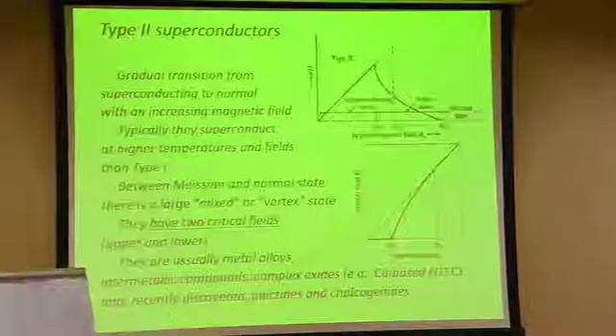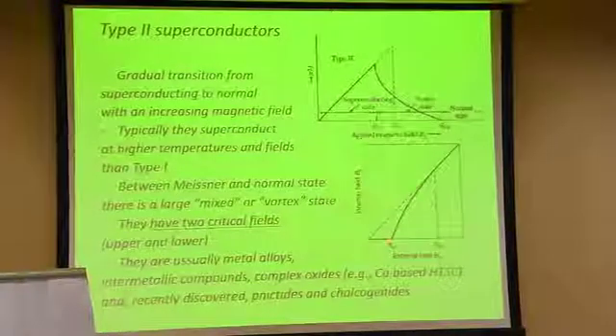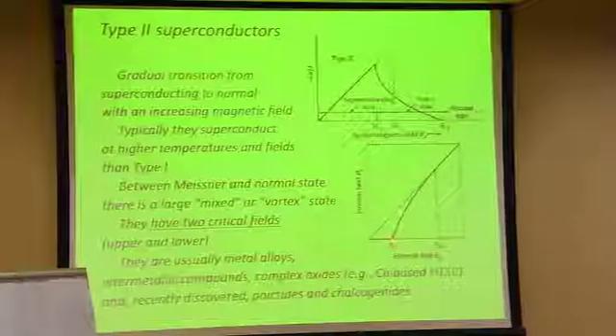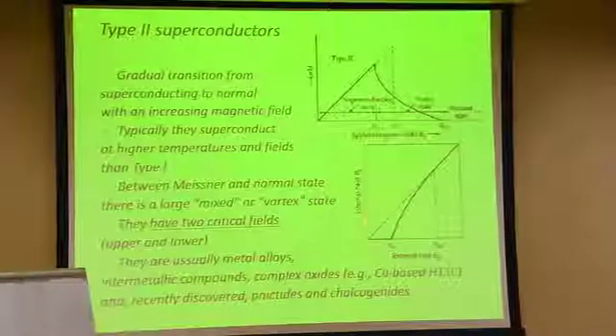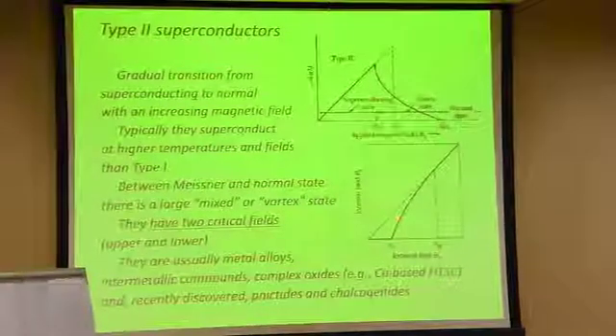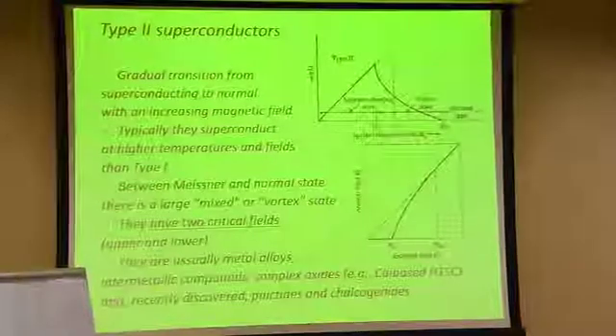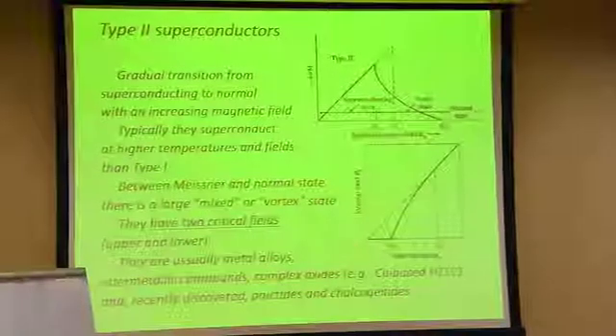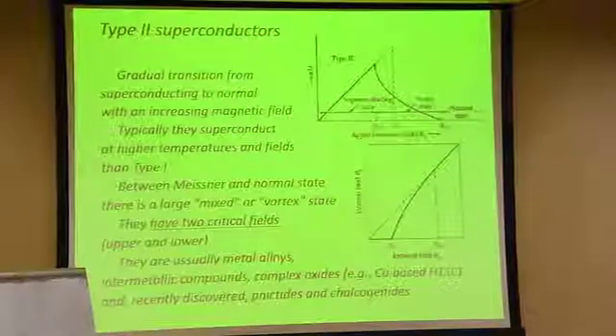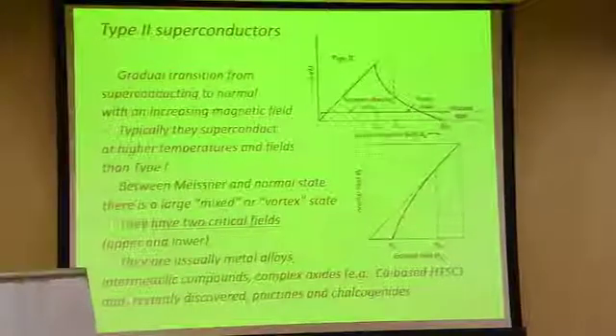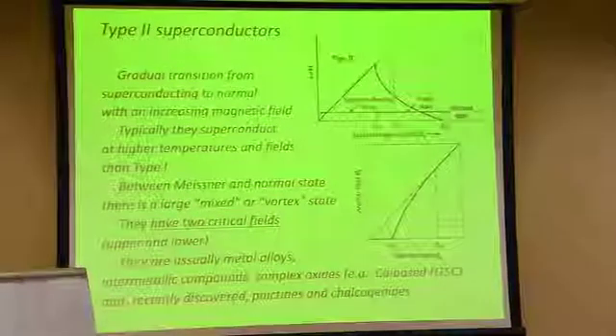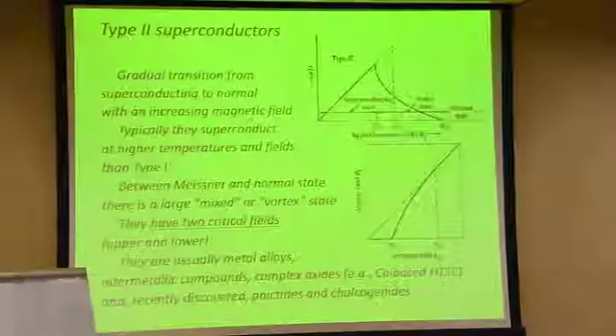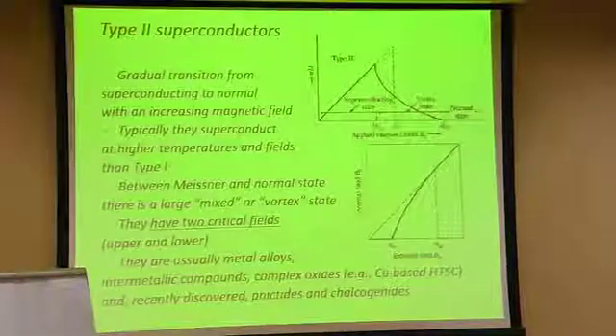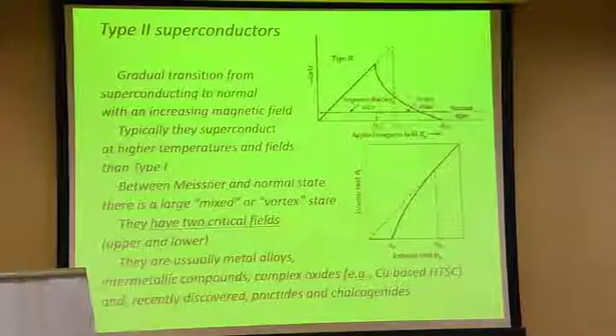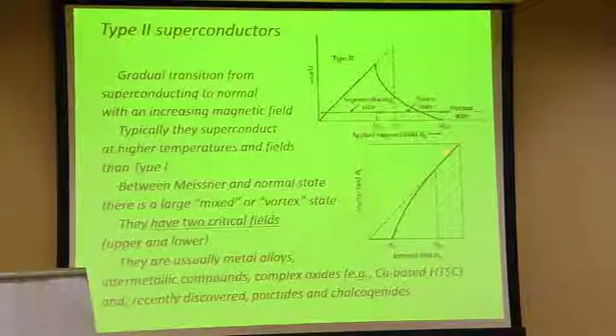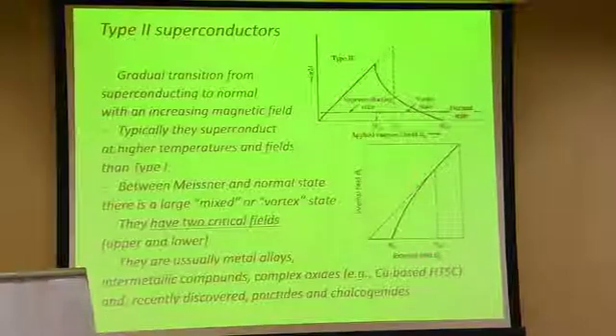Now, if we look at the internal field in the material, between 0 and quite a small lower critical field, BC1, the internal field inside the material is 0. After we increase the field further, then we do have an internal field in the material. And we will see later on that that internal field in the material is actually formed by flux quanta, which are called vortices. And when we reach the upper critical field, we get back to the straight line with slope 1, and we go into the normal state.